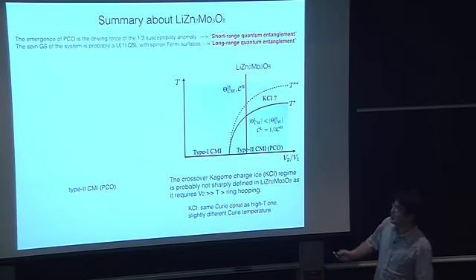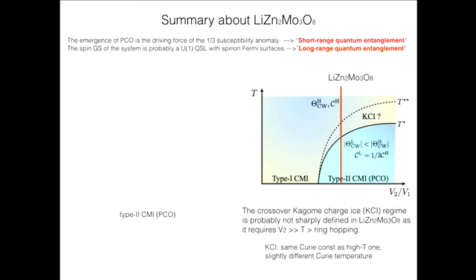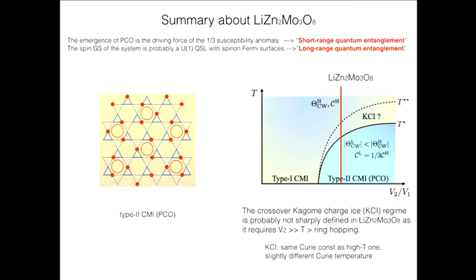So let me summarize this simple picture. The emergence of the plaquette charge order is the driving force for the 1/3 spin susceptibility anomaly. In fact, if I use the fancy language, this is the short-range quantum entanglement creating the 1/3 spin susceptibility anomaly. And the spin ground state is a U(1) spin liquid with a spinon Fermi surface. That's a long-range quantum entanglement. So that's the pattern of short-range entanglement, if you like. That would be a schematic phase diagram.